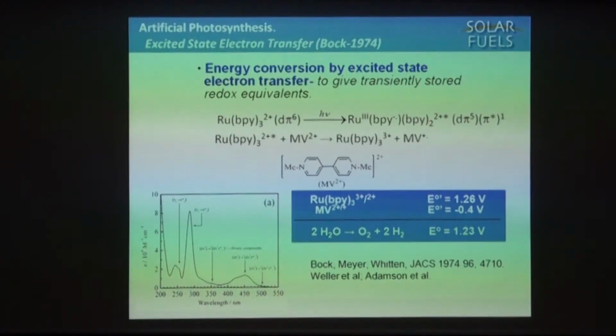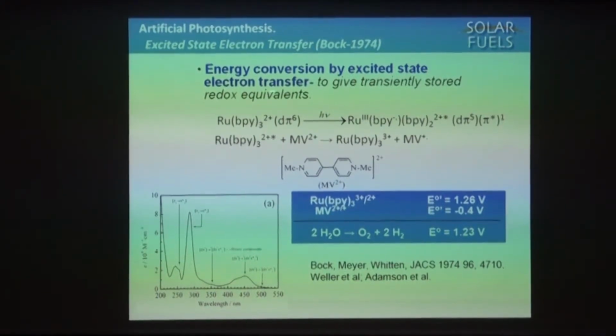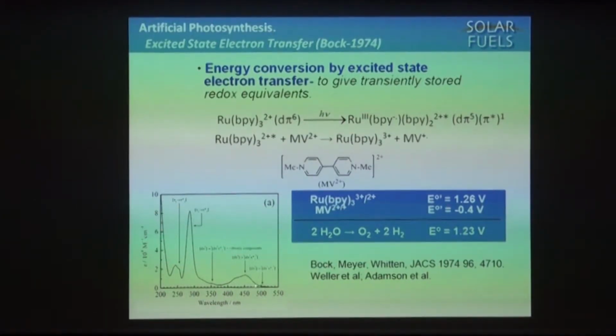There was another observation at the same time frame. It actually came from my group in collaboration with my friend Dave Whitten at UNC many years ago. And what we showed using flash photolysis was that you could take this transition metal complex, the famous Ru(bpy)3, which is coordinatively stable. It absorbs light in the visible. Here's the absorption spectrum. Notice here's 400 nanometers, here's 500. So in the visible part of the spectrum, at least the high energy part, it's a respectable light absorber.